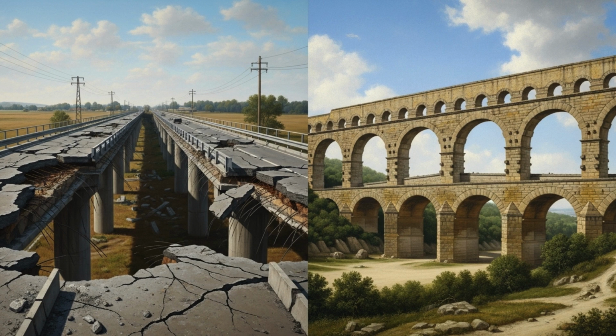Flaw 3, permeability. Modern concrete is porous. Water penetrates it. In cold climates, this water freezes and expands, causing internal damage. In marine environments, chloride ions penetrate and corrode steel reinforcement. Roman marine concrete becomes less permeable over time as new minerals fill the pores. Flaw 4, no self-healing. When modern concrete cracks, it stays cracked. Repairs require external intervention: epoxy injections, overlays, or complete replacement. Roman concrete repairs itself, continuously, for centuries.